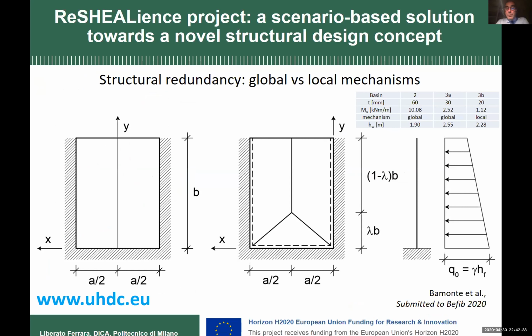We used the yield line mechanism approach to predict the performance, and we realized that even with 2 or 3 centimeters thickness, our slab was safe, and we were able to withstand a surcharge weight much higher than the height of the wall.